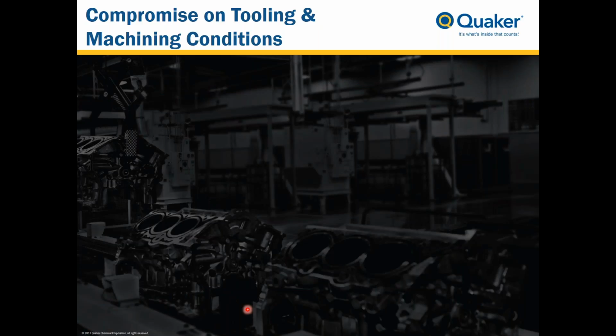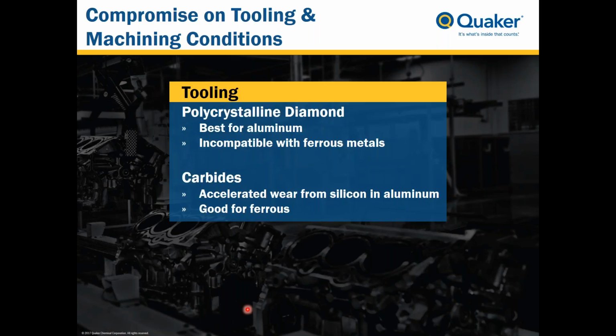The second factor that contributes to the difficulty in machining, as I mentioned, is that typically there's a compromise in the tooling used and the machining conditions. I'd like to present at least two examples of this. And one is the tooling. Typically in machining aluminum, polycrystalline diamond or some form of synthetic diamond cutting tool is best suited. You're going to get your best finish. You're going to be able to run at considerably higher cutting speeds and feed rates using PCD cutting tools.